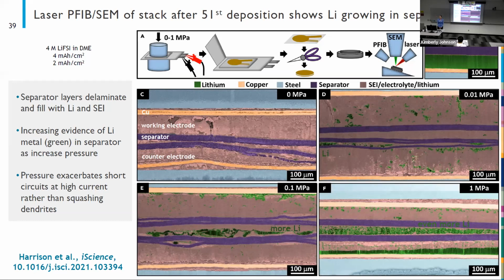Yeah, that's a great question. And we didn't look at that in particular, but there's some really nice work by Craig Arnold. And he has looked at lithium ion batteries where he looks at the separator and tries to understand where it starts getting damaged. And I think in his results, he shows that at about 1 megapascal, you start seeing viscoelastic creep of the separator and you start to shut down the pores. And he has beautiful images just showing how the pores go away and sort of become this mess. And so we think even at 1 megapascal, we're probably getting a little bit of that. And that's more than you should use for Celgard separators. But we haven't looked into it. I just trust Craig Arnold.